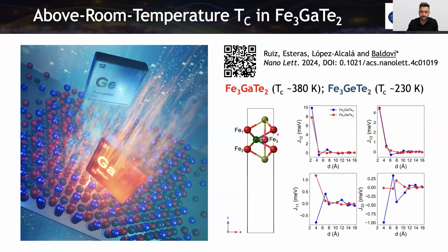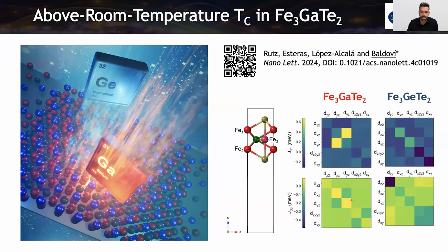We also explored the possibility of having a monolayer of iron gallium tellurium, and we calculated the phonon dispersion, and the system is stable, so it's possible to exfoliate it down to the monolayer limit. And we could observe the same behavior. So these are 2D properties, and it is clear here that this behavior is the same as in the previous slide with the bulk.